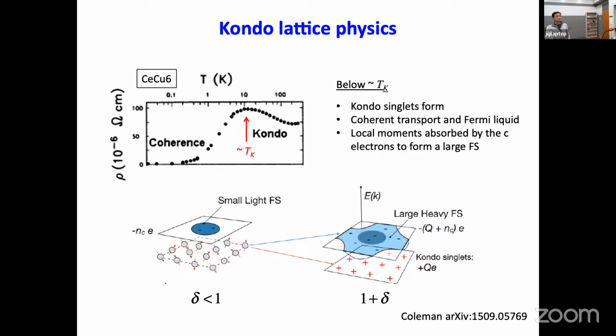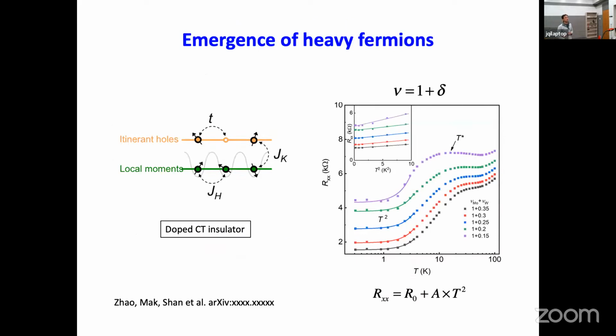So before the absorption of the local moment by the itinerant carrier, we would expect a Fermi surface with doping of delta, where delta is the average number of electrons per Moiré unit cell, less than 1. But once you form a heavy Fermi liquid, you would expect the size of the Fermi surface to become 1 plus delta, which is a large Fermi surface. Okay, so these are the two things that we would check. We would check the emergence of coherent transport at low temperature, and the change in size of the Fermi surface.